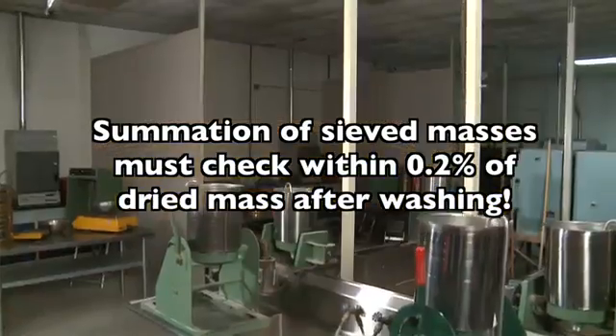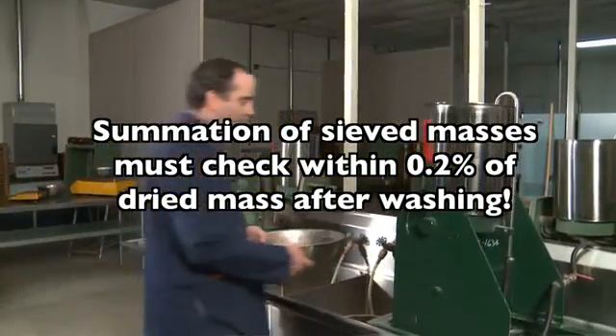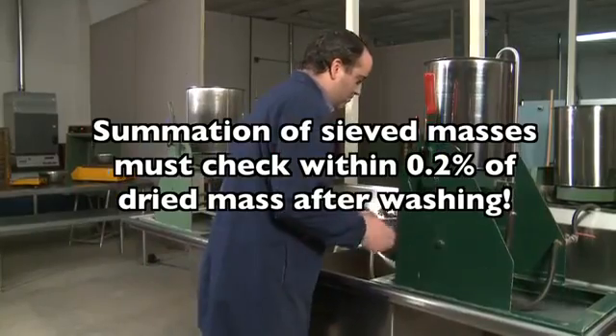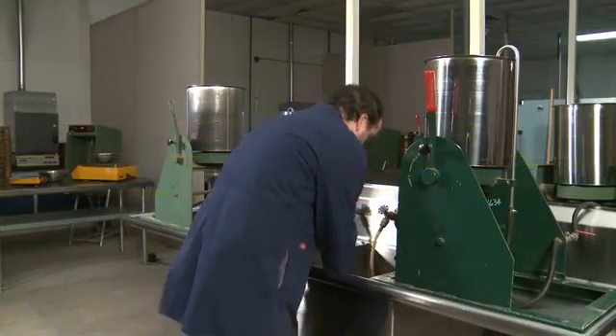To ensure that a substantial amount of material was neither lost nor gained during the sieving process, the total of the masses after sieving must check within 0.2% of the dry mass of the extracted aggregate after washing.